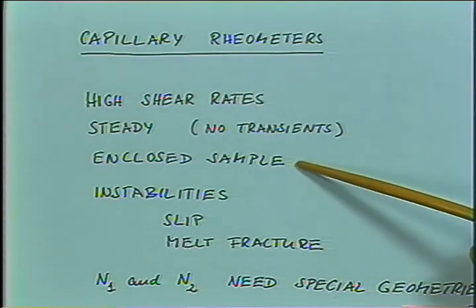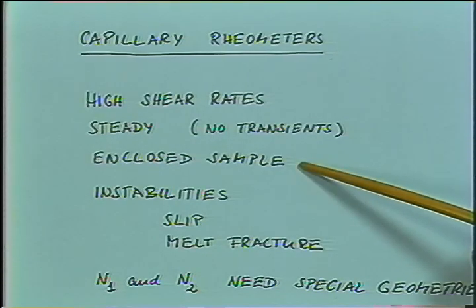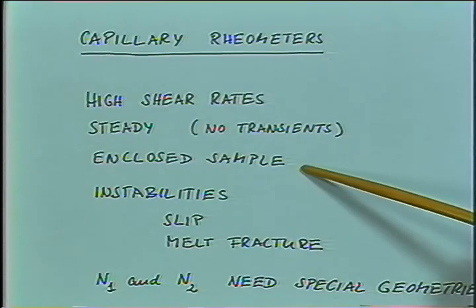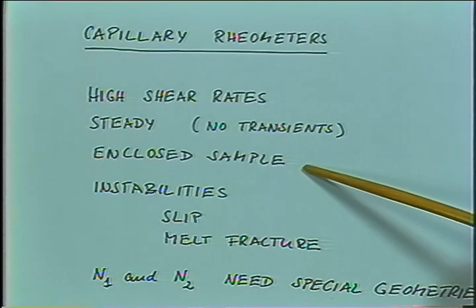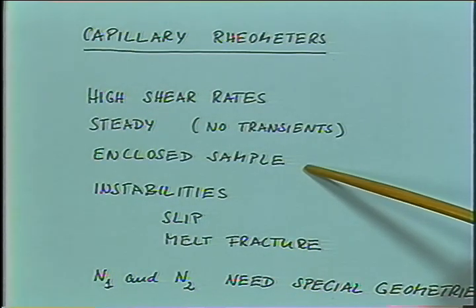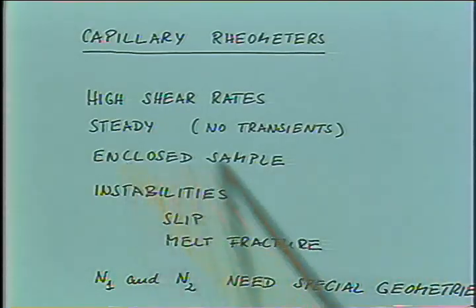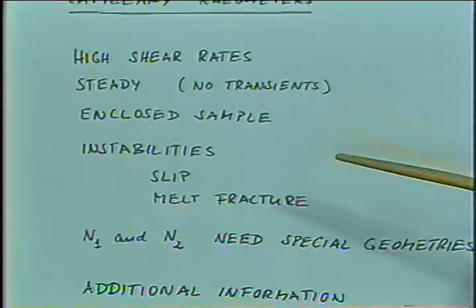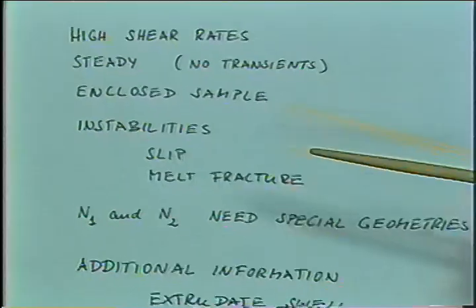The sample is enclosed in all conditions. It doesn't have a free surface, which is nice when you work with polymer solutions or with degrading materials or have oxidation effects. It's a major advantage. You might lose that advantage when you fill your capillary rheometer with pellets, which have a lot of surface area. Then during the heating process, you still might get your degradation and all kinds of effects. But if we do it right, we have an enclosed sample and we will be pretty safe.